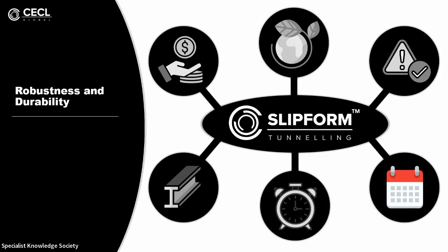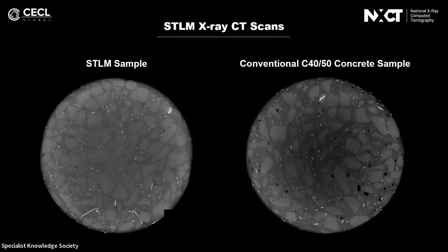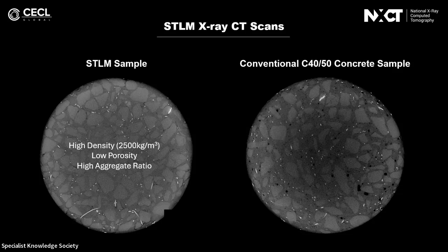Onto the robustness and durability aspects and the testing and analysis we've done here. So firstly, a qualitative look at the STLM structure from peering inside these samples using X-ray CT scanners from some assistance from the National X-ray CT Centre, which has a base at the University of Warwick. So it's apparent that the STLM samples are tightly packed, a high aggregate ratio in their compressed form and low porosity, and a high density of 2,500 kilogram per meter cube or higher. And this qualitatively suggests that the lining would be very durable in the long term.